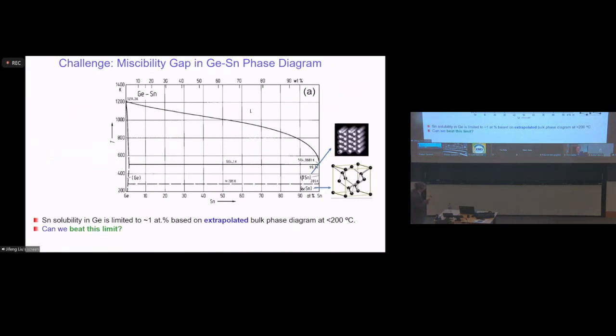There's a caveat to this approach, because for material scientists, the first thing you want to check is, I want to use this material as an alloy, germanium tin. Germanium has a small band gap, 0.666 electron volts. Tin is essentially a semi-metal, which means zero gap. Somewhere in between, you should be able to get the band gap you desire for infrared detection. But the question you want to ask is, do they actually mix?